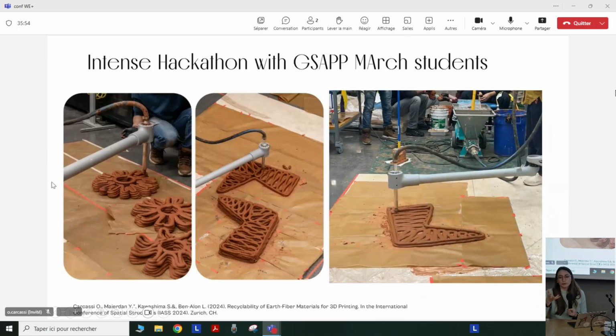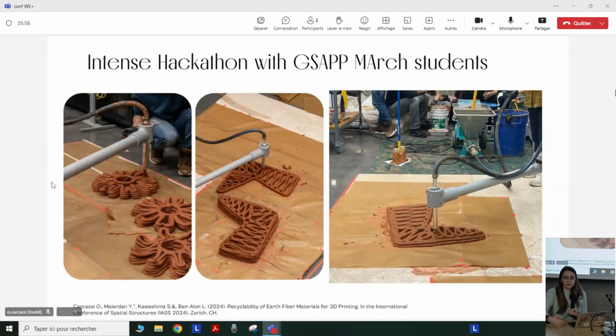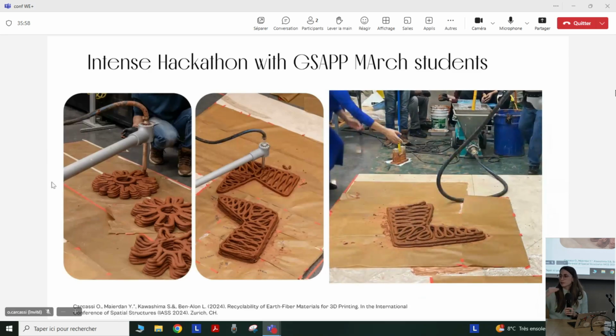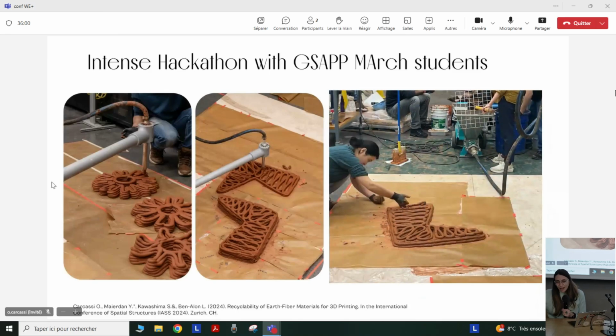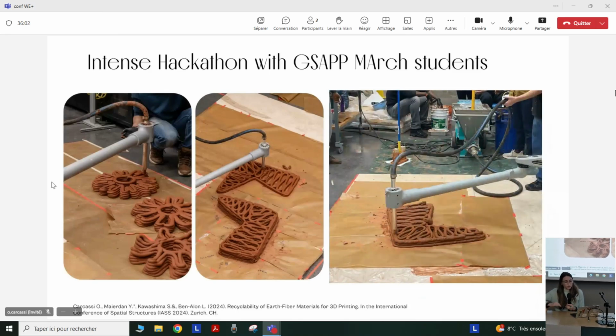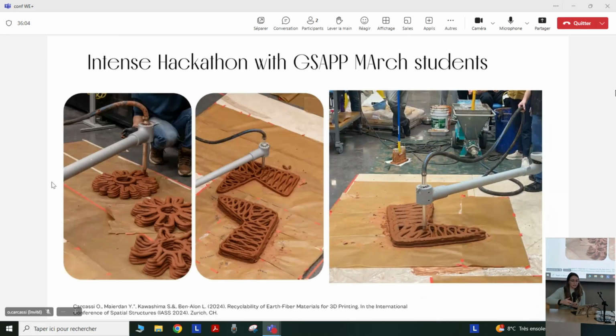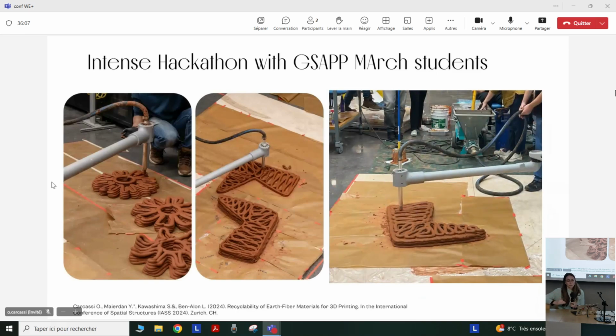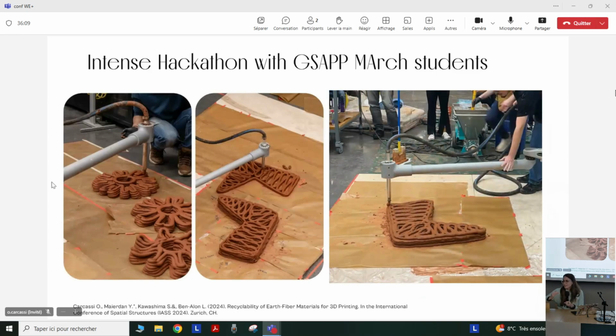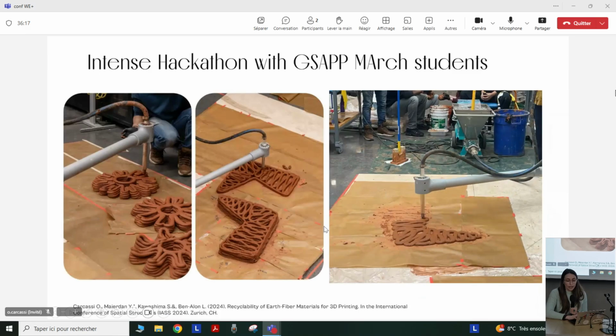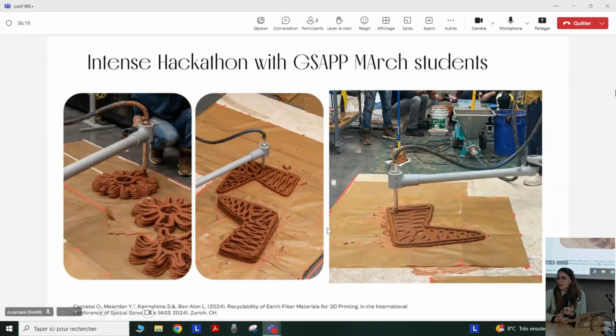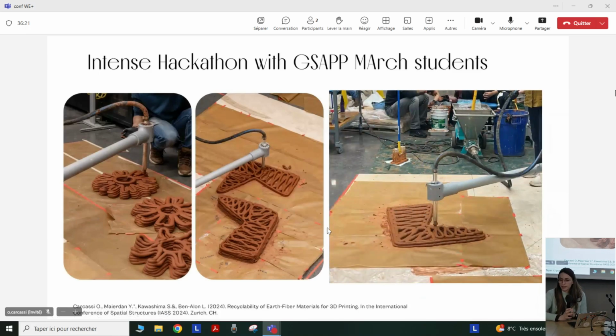When you work with Earth, you need to print a certain amount of layers, and then you need to wait for the day after to be fully dried, so you can print again on top of it. So by only having 5 days, we could only achieve a limited height of elements, but nonetheless, it was very interesting. And what I want to really show you here in this video is how forgiving Earth is. This is something that you cannot do with cement and concrete.